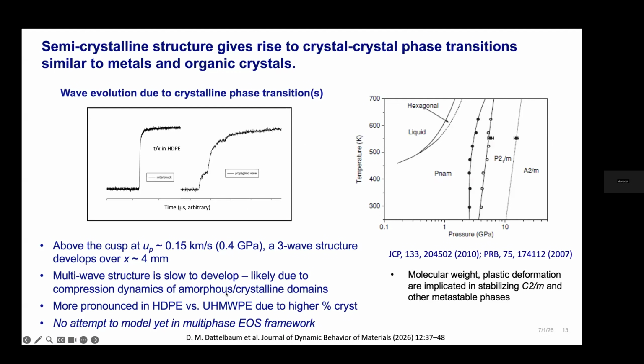So the only way we can really detect this is by running the wave and looking at the wave over time and distance. And it turns out these transitions also occur quite sluggishly, like it takes almost 4 millimeters for that multi-wave structure to develop in the material. And at least at LANL, and I don't believe anywhere else, there's been no attempt to model that yet in a multi-phase equation of state framework.